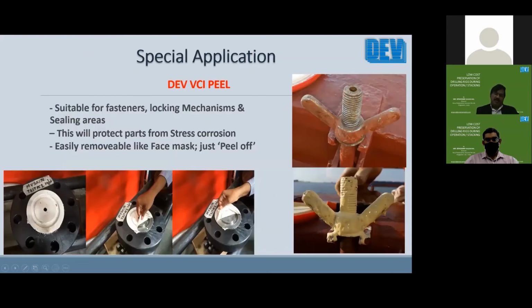This is like a face mask. This is one of the products which I love because this one is very simple to apply, which provides multiple benefits. This can be suitable for outdoor use, for protecting precision faces, as well as to protect parts which have stress corrosion issues. We had seen in many stainless steel pipings, the straight pipe was okay, but the bends used to have stress corrosion problems. In those cases, just by applying one coat of this VCI film, the stress corrosion issue is eliminated, and this particular film can be removed. Like in the case of gasket faces or fasteners, when they want to remove it, this can be peeled off like a face mask, and then the part can be accessed.